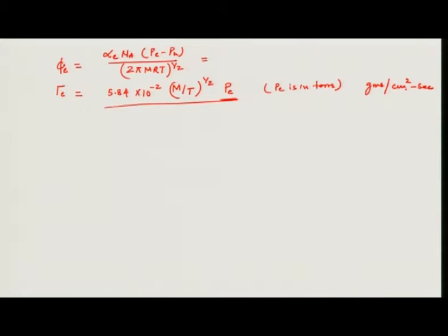to vapor phase. Okay. Now, from this we also had derived an equation to know how the vapor pressure changes with temperature, which is an exponential relation, and it depends on the enthalpy of evaporation or molar heat of evaporation. How much heat is released or absorbed when 1 mole of material goes from condensed phase to the vapor phase. So, let me write this as P E because we are using P E term here. Okay.